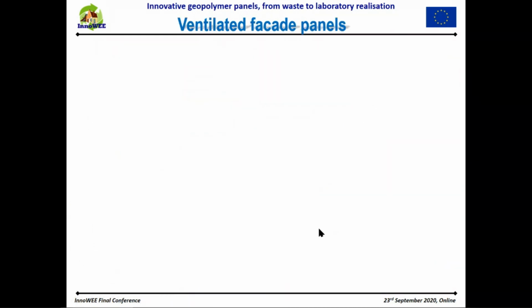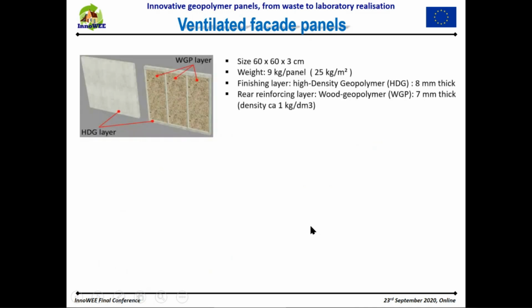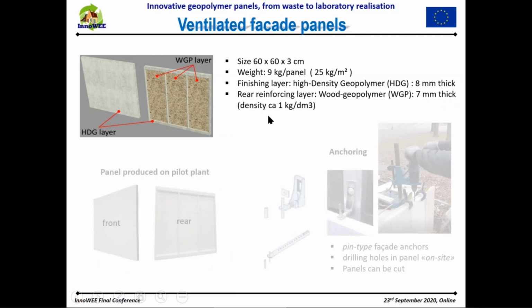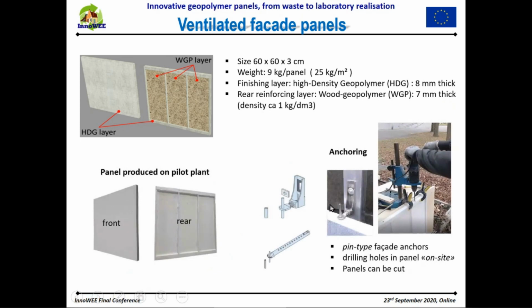Talking about the ventilated facade, the dimension is 60 by 60 and the weight is 25 kilograms per square meter. It is built as before, with 8 millimeters of high density geopolymer plate, reinforced with geopolymer ribs of 3 centimeters and metal fibers. In the back, we have used a particular kind of geopolymer made with wood to improve the impact resistance. It can be mounted on a metal structure with a special anchor system.